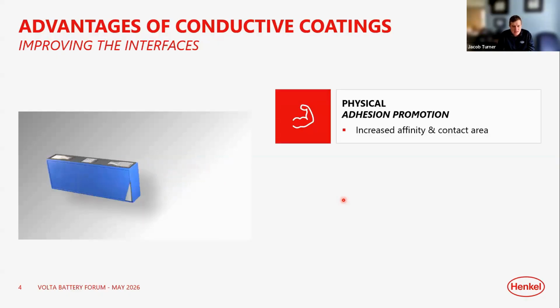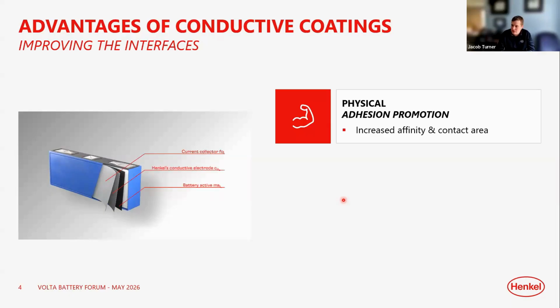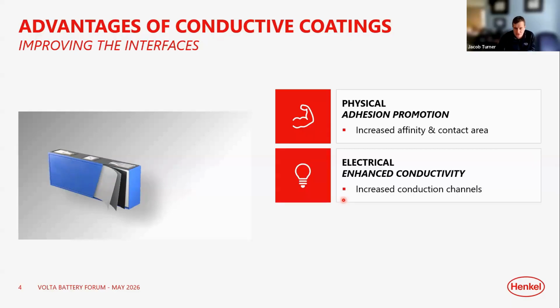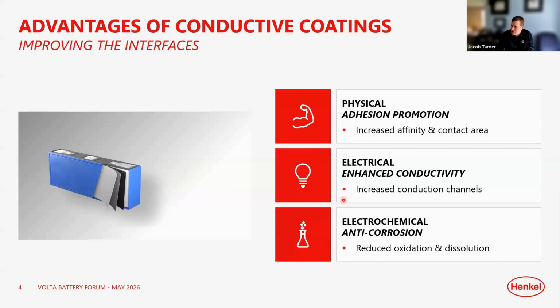So we get into these buckets of where we see areas of improvement when using these conductive coatings. We'll walk through it today, but it does depend on how you're manufacturing electrodes and the materials being used as to where that core advantage comes from. And there's also not a one size fits all conductive coating. It's important to design this interlayer material appropriately for the use case. Our three buckets are largely physical adhesion, electrical conductivity enhancement, and then some anti-corrosion electrochemical protection that it provides, purely as a barrier coating.